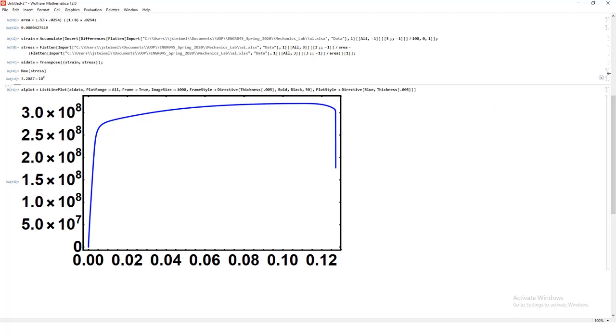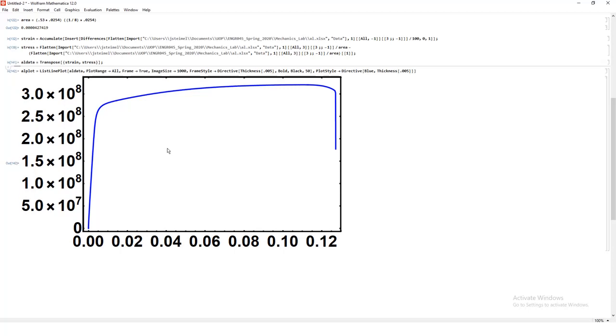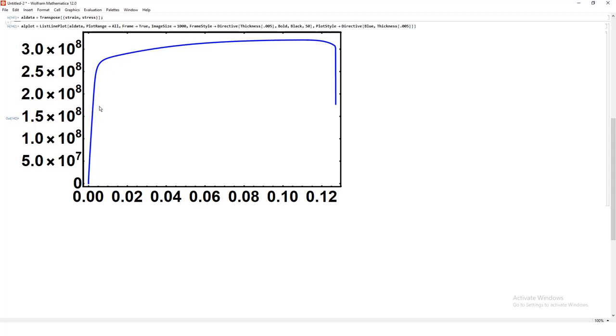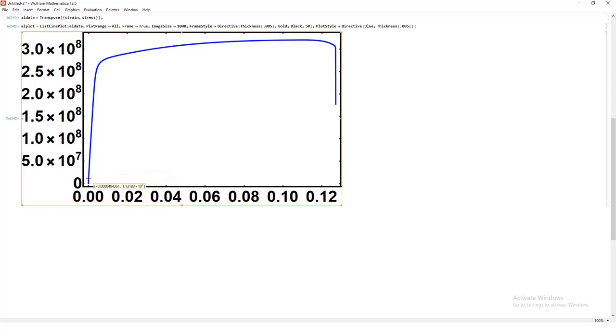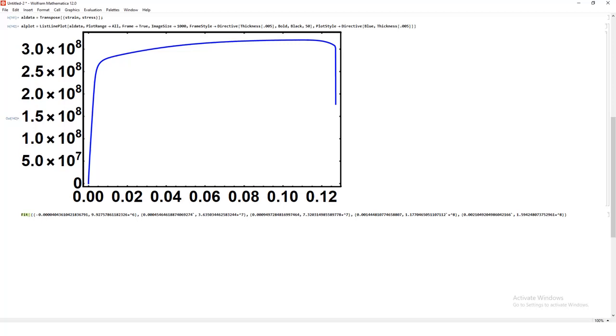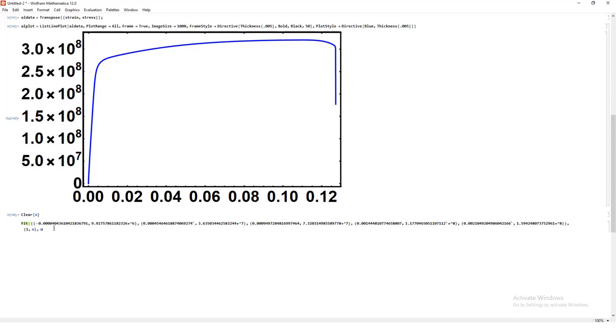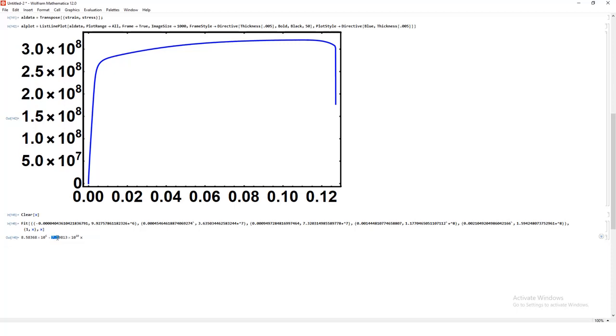But one of the harder problems to solve, or one of the harder quantities to measure, is going to be the Young's modulus. We know that's just this linear region, right? So we need to find the slope. Luckily, in Mathematica, we can approximate the slope by just grabbing some of these points. So I'm going to grab a couple of these points. And that's pretty sufficient. I'm going to Control-C, and I got my points here. So these are my data points. I want to fit this with a linear function. So 1x. I'm going to clear. It's like x is defined somewhere. I need to clear that. That's from my previous notebook. We need to make sure if it's blue, it's a variable. If it's black, it is already defined. So I want to fit this. And what is the Young's modulus of aluminum? Typically, it should be about 69 gigapascals. So here, about 72 gigapascals. That's pretty good. That's pretty close approximation. That is a nice result here.